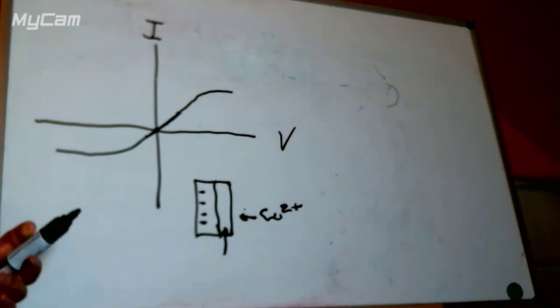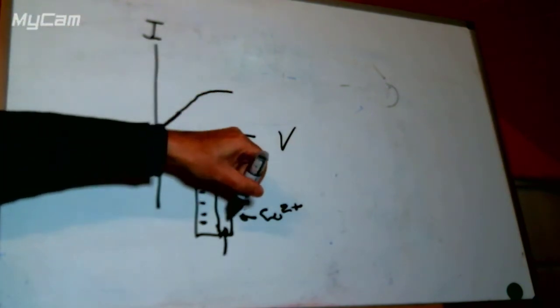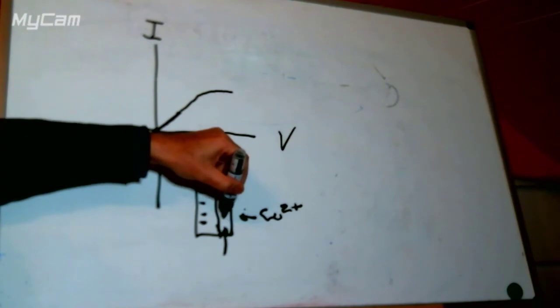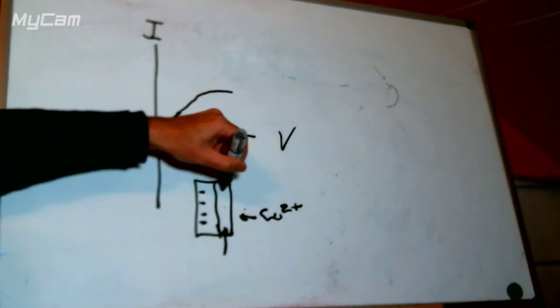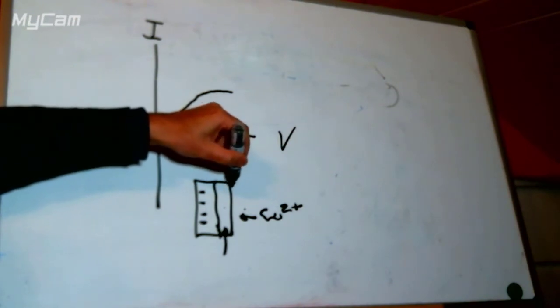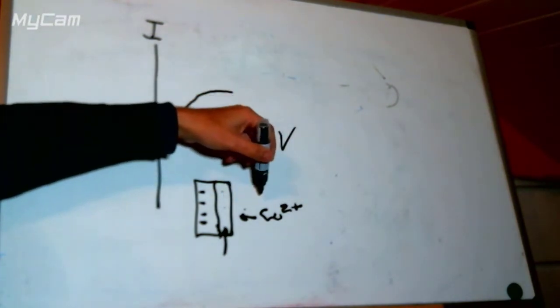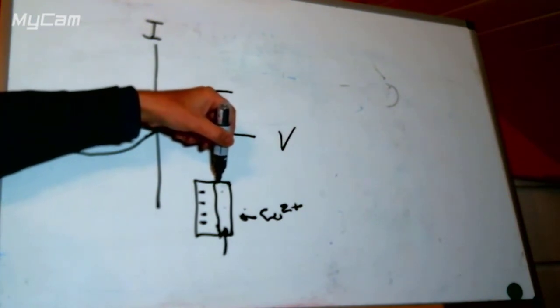And it does to a certain extent, but not nearly as much as we would expect, because we make our electrode negative. There are other ions in here that are positive. So in this case, it would be positive hydrogen ions, for example, depending on what the solution is. Or we just push away the sulfate ions, making this area relatively positive. Relatively positive.